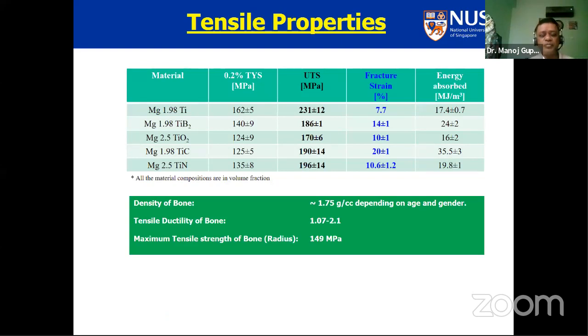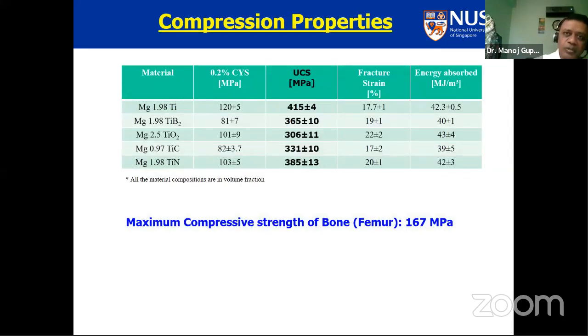Since we are using nano size reinforcement, you see in this table that the amount added to magnesium typically does not exceed 3 weight percent. Look at the UTS value—it's typically higher than the strength of bone, which is 149 megapascal. The fracture strain is again much higher than the tensile ductility of bone. So these materials, in a way, are stronger and tougher than bone. From a mechanical perspective, they qualify.